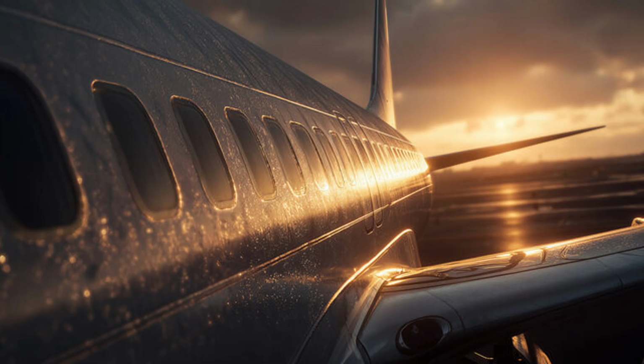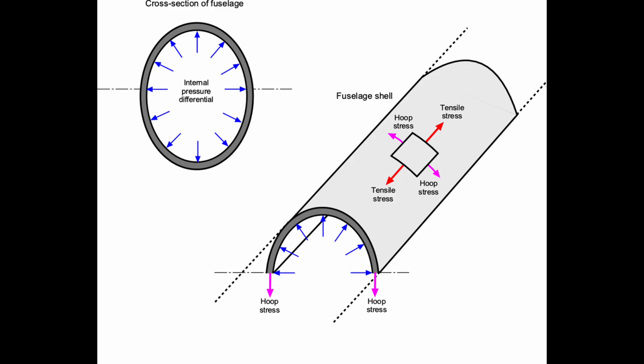If the fuselage skin ruptures, the pressurized air inside the cabin accelerates toward the opening, tearing at the structure with explosive force. This is not an explosion in the chemical sense, but the effect is just as violent. The rapid decompression produces a shock wave that can rip panels loose, collapse floors, and impose enormous transient loads on the airframe. The failure often propagates along structural seams, following the path of least resistance, unzipping sections of the fuselage skin. In extreme cases, large portions of the aircraft can be torn away, exposing the interior to the open sky.